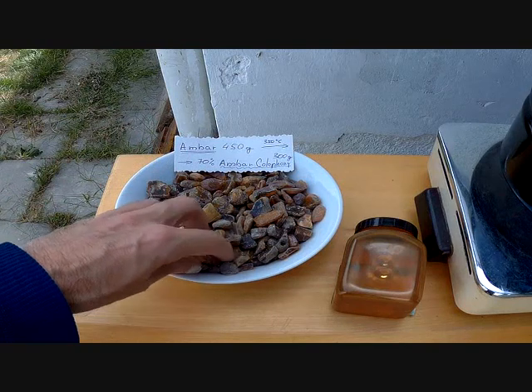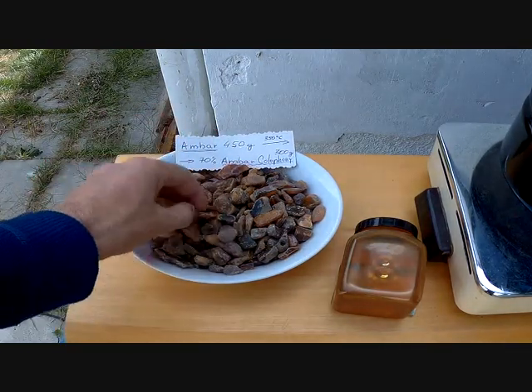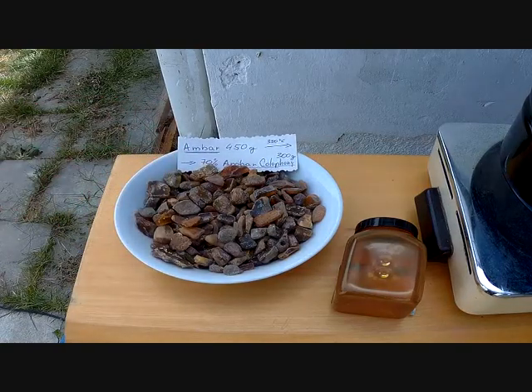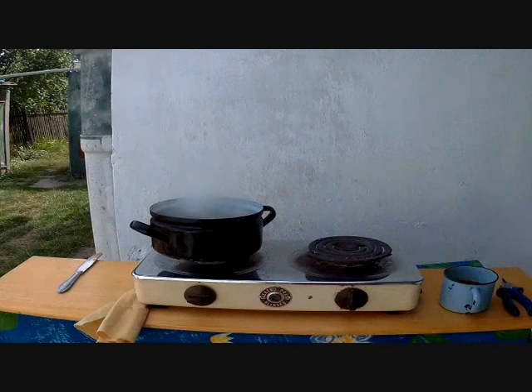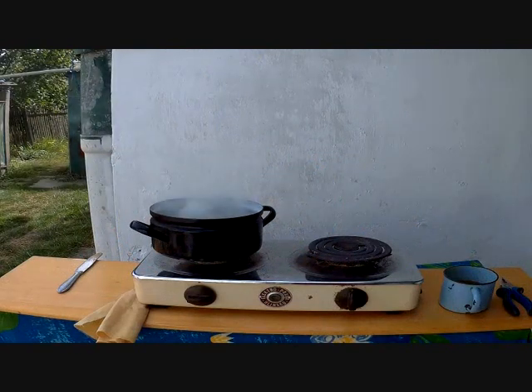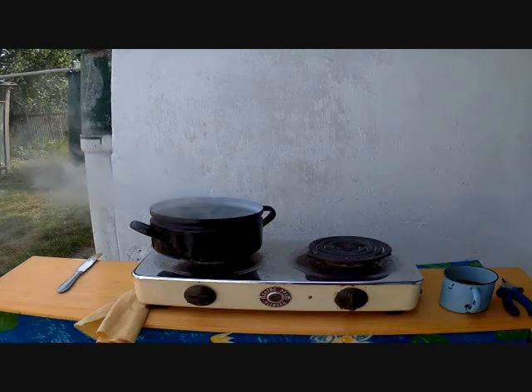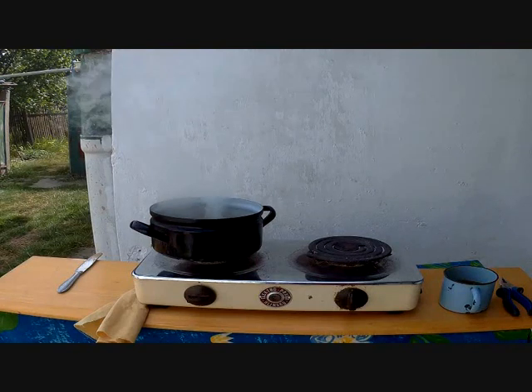After we take these small pieces, we put them into the pot and apply direct heat — without oil, without anything. We wait a little time. At 350 Celsius the amber starts to melt, and the white smoke produced is amber acid.